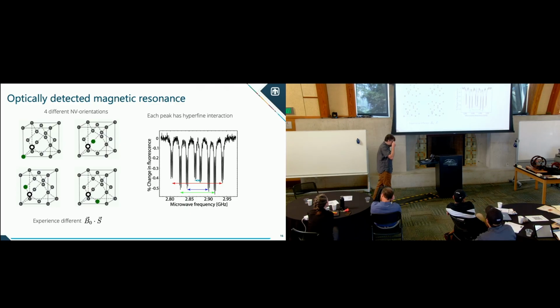If we look at a spectrum here, this is from Victor Acosta's thesis. I take a lot from Victor's thesis, it's very good. If you put it at an arbitrary angle, you can actually see 4 different sets of 2 peaks. For the 4 different orientations, 1, 2, 3, 4, that's 0 to -1 on this side, and on this side it's 0 to +1. So you have 8 different main peaks, and then each of those has 3 subpeaks.